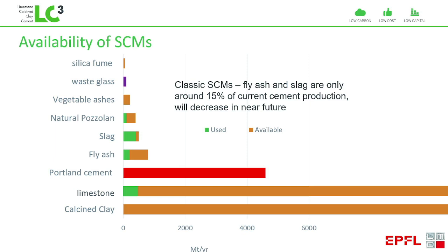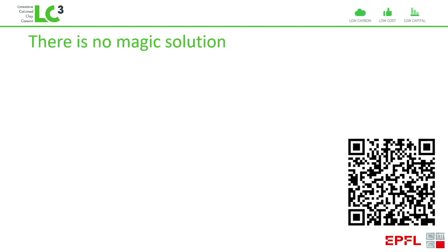So this is where we started from, and we looked at what materials we could use as alternatives. Limestone is widely available, but the problem is it has low reactivity. And then we came to the clays. Clays can produce very reactive materials when they're what's called calcined. That means heated in the range about 800 degrees.